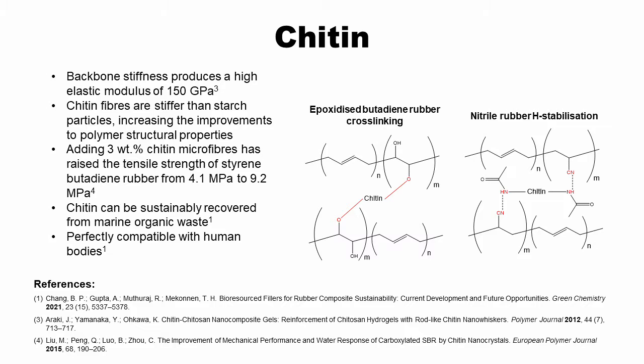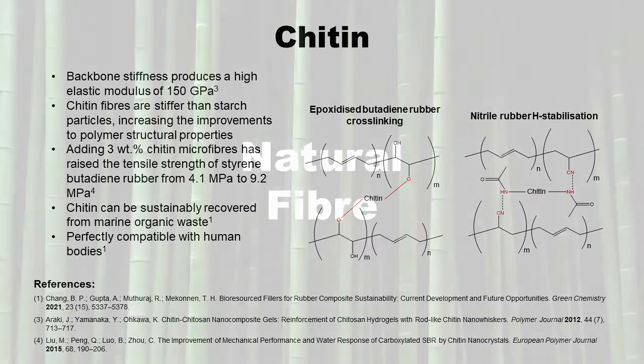The increased backbone stiffness of chitin has given chitin fibers an impressive elastic modulus of 150 gigapascals, which allows it to improve the structural properties of polymers more. Adding 3 weight percent chitin microfibers has raised the tensile strength of styrene butadiene rubber from 4.1 megapascals to 9.2 megapascals, a more than twofold increase. Chitin can be sustainably recovered from marine organic waste, and it's perfectly compatible with human bodies.